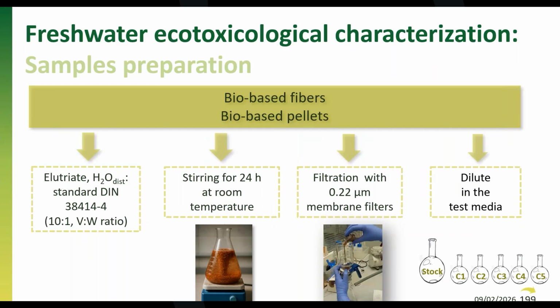Then just very briefly for the bio-based fibers and bio-based pellets, as I mentioned, we needed to generate the leachates, the eluates, and this is easily done by using this ratio of 10:1, and then leaving this mixture by stirring for 24 hours, and then we just filtrate the water and then dilute this water for the 5 concentrations to be tested in the acute toxicity assays. Next slide, please.